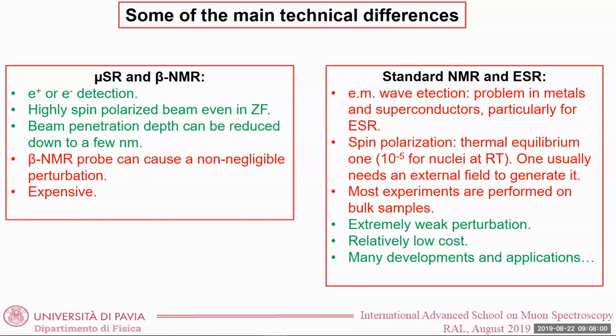And considering that the Zeeman splitting that you have in, let's say, an NMR experiment is very small, and in particular is much lower than the thermal energy, at the end of the day, the polarization that you get in an NMR experiment is of the order of 10 to the minus 5, which is basically telling us that just one nucleus out of 100,000 will contribute to your signal, while in the MUSR, all the muons will give you a signal and contribute to your polarization. So let's say this is standard NMR, and in standard NMR we have this problem of low polarization.